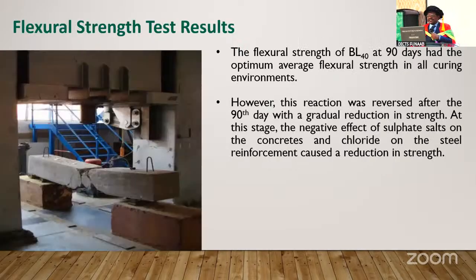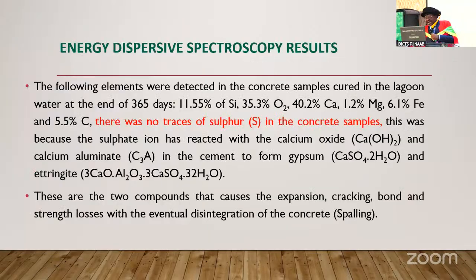For the flexural test, BL40 at 90 days had the optimal average flexural strength in all the curing environments. However, this reaction was reversed after the 90th day with a gradual reduction in strength. At this stage, the negative effect of sulphate salts on the concrete and chloride on the steel reinforcement caused a reduction in strength. Now, we carried out the energy dispersive spectroscopy in order to know the chemical compounds in the concrete.